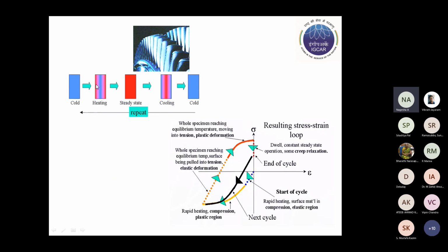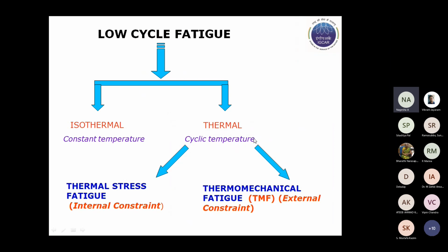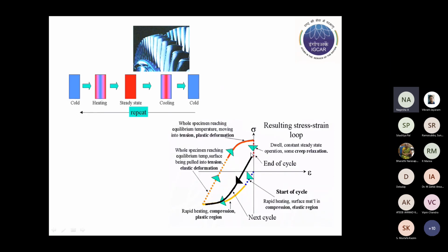The surface gets hot first, and though it is able to expand externally, it is restrained by the colder bulk. So this gives rise to a compressive stress on the surface. And when the steady state is reached, the entire component gets heated up and it goes from compression, it drives it to tensile. So during the steady state operation, the creep deformation, etc. is taking place, and there is a relaxation of the stress. So this is the end of the cycle. This relaxation takes place due to the creep deformation, wherein we have conversion of some of the elastic strain into plastic strain. So this leads to a reduction in the stress. And at the beginning of the next cycle, the same thing gets repeated.